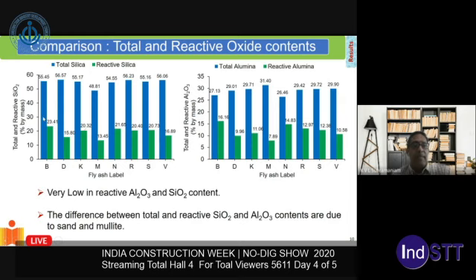Now, if you look at the same 10 fly ashes, the blue bars represent the total oxide contents of the fly ash, and the green bars represent the reactive oxides. So if you see here, now the differences start showing up. While the blue bars are almost comparable for all fly ashes, in the green bars, there are a lot of differences in the reactive oxide content. First thing to note here, the reactive content is much smaller than the total oxide content. That means only a small portion of the total silica and the total alumina in the fly ash is available in a reactive form. And it can be as small as 13% of the total silica being reactive, and about 7 or 8% of the alumina being in the reactive form.